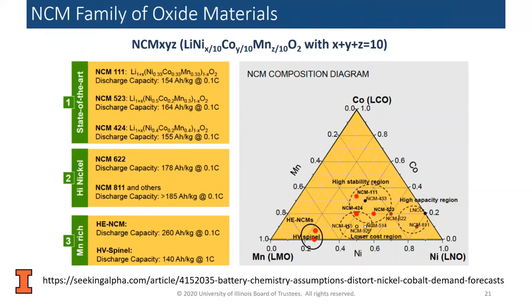And so basically what they're doing is they're taking mixtures, at least in this case, of different, they'll take a certain amount of, let's say, LNO, so lithium nickel oxide, and then lithium cobalt oxide, lithium manganese oxide. So basically you'll have, in this case, the 811, you'll have 8 parts of the LNO, and then 1 part each of the LCO and LMO. So that's basically how, and then they mix them together and then they produce their battery. So does that answer the question?